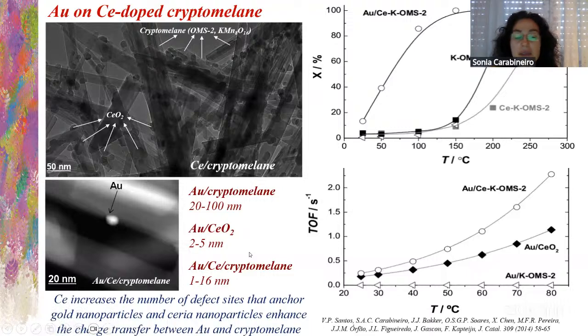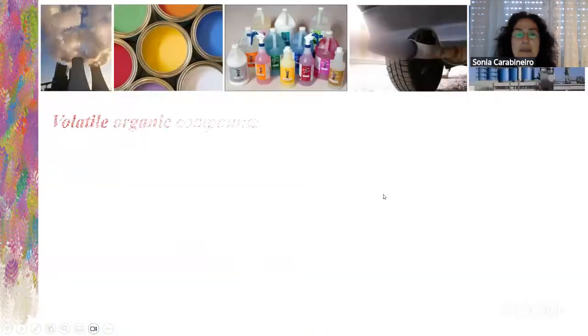So what we found out is that cerium increases the number of defect sites. Remember before, also with the copper samples, the defect sites were good for the activity. So these sites anchor the gold nanoparticles and enhance the charge transfer between gold and cryptomelane.